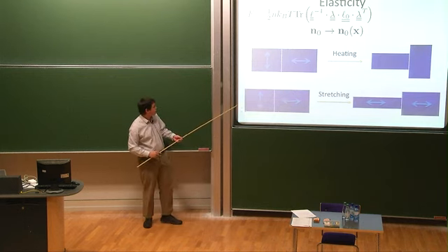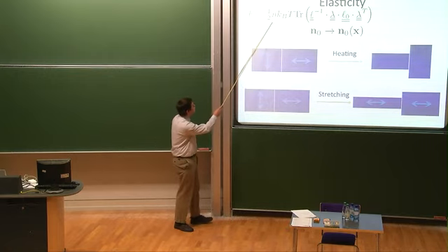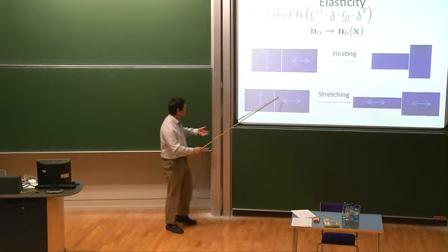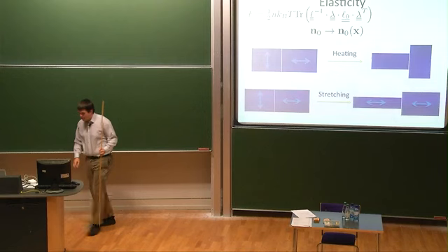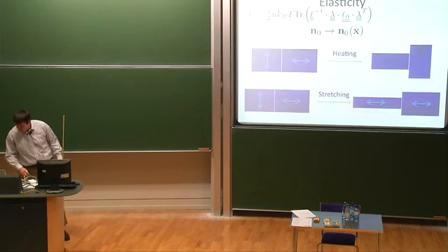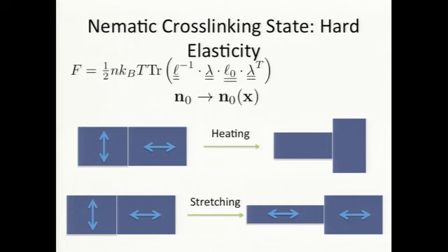Okay, so they're geometrically constrained. So even if I put in a perfectly soft local energy, my expectation is that this is going to be hard. Now, I'm saying expectation quite carefully. Okay, I should say, so this is the energy you now use. So this is the energy you get, the perfectly soft energy if you cross-link with some order n L0 in the nematic state. And then the idea is now this L0 should follow a typical nematic liquid defect pattern.